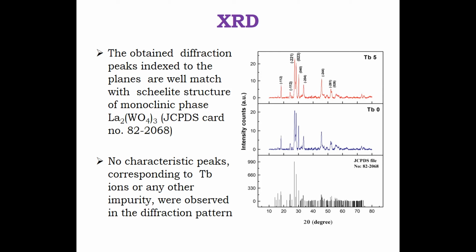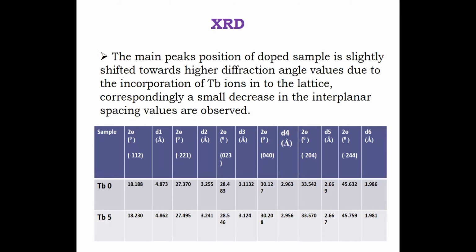Next slide. But the main peak positions of the doped sample are slightly shifted towards higher diffraction angles due to the incorporation of terbium ions into the lattice. Correspondingly, a small decrease in the interplanar spacing values is observed in the terbium doped sample, and it is tabulated in the given table.